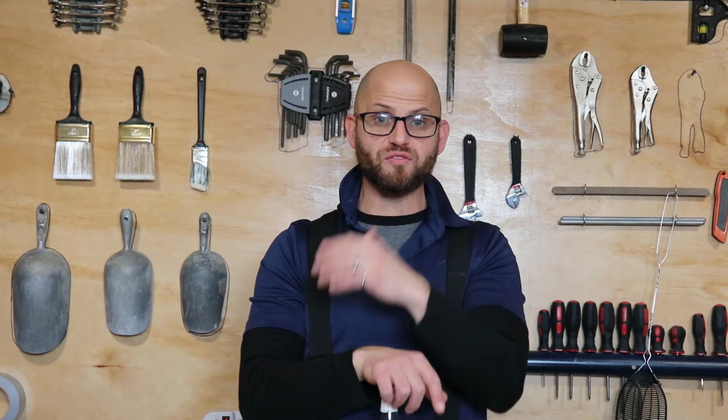concrete is not the best substrate, especially with the alkali content and the moisture content. So unless you have a very good concrete that has limited vapor emission and limited salt migrating to the surface, you want to put some type of a coating or a primer over that to limit the moisture and the salts that would cause the adhesives of our vinyl flooring system to go through hydrolysis, break down, and then from there you get delamination. So yeah, an epoxy urethane combination is not bad.